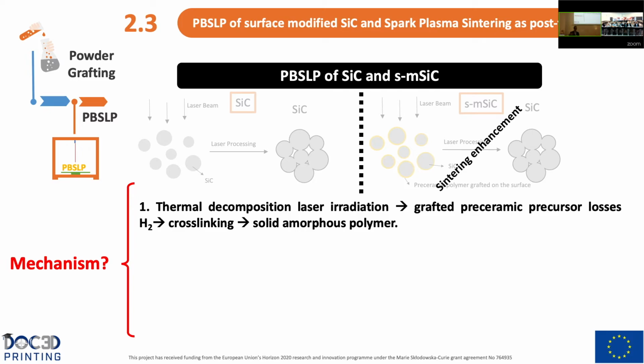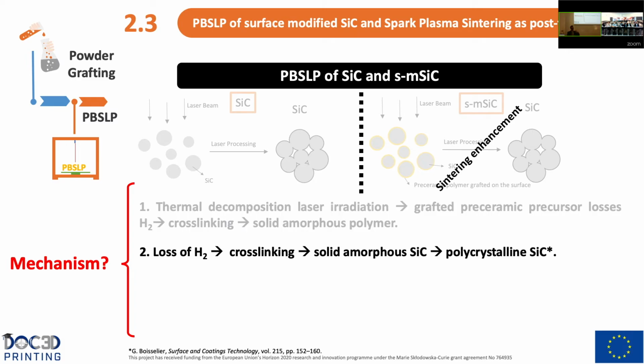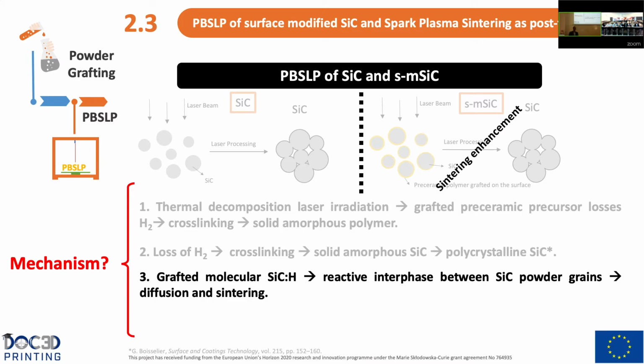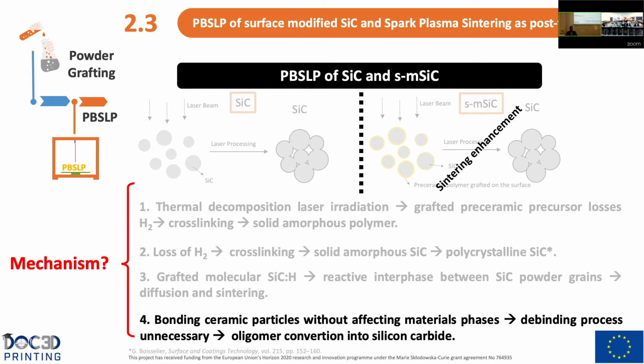We will lose hydrogen, leading to cross-linking, and we create a solid amorphous polymer. Then, by continuing this loss of hydrogen, leading again to cross-linking, we will form a solid amorphous silicon carbide that will be converted into polycrystalline silicon carbide, as it is reported in the literature. Next, this grafted molecular silicon carbide hydrogen layer will create a reactive interface between SiC powder grains, facilitating diffusion of sintering. And finally, this will produce the bonding of ceramic particles without affecting the material phases, making the debinding process unnecessary and actually fulfilling the original conversion into silicon.